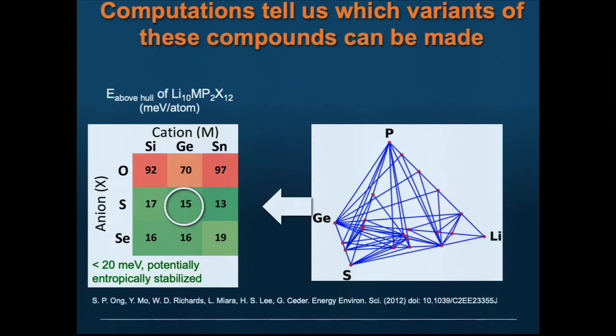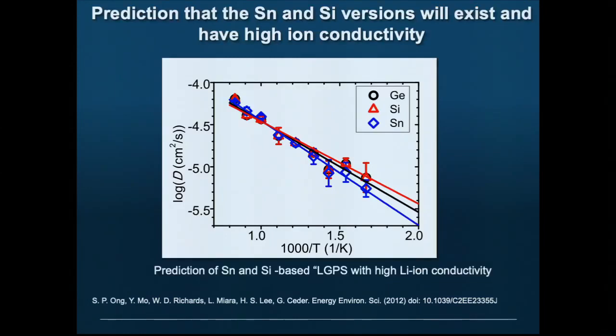So the sulfur germanium version is metastable by about 15 millielectron volts per atom. But what you see is, if you go to tin or silicon, that doesn't change dramatically. Or if you change sulfur to selenium, that doesn't change much. So in principle, these should be able to be made. You can calculate, they have similar conductivity.